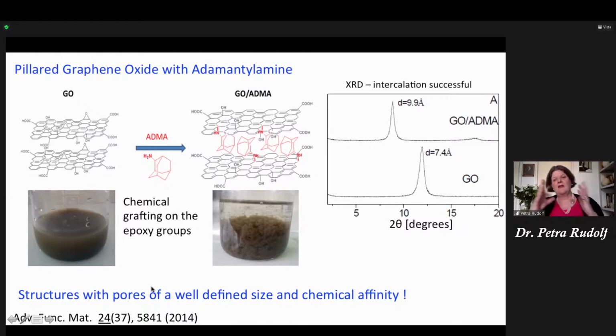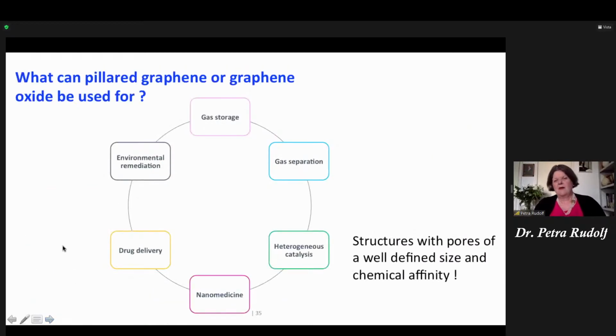And the nice thing of these structures is that you create a material which is porous, but the pores have a very well-defined size, because the size is given by the distance between the planes, which is determined by the pillars that you put in. But by putting the right kind of molecule, you also create a pore with a certain chemical affinity. And we have been doing that for quite a few years by now, and I'm going to show you some examples of it. What can you use these pillared graphene or graphene oxide for?